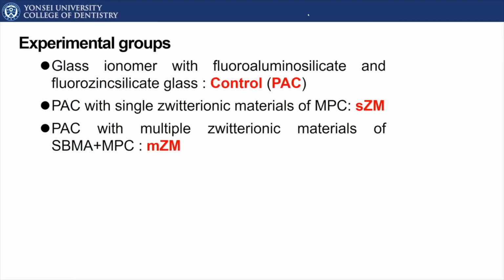So here, what we prepared was glass ionomer with fluoroaluminum silicate, but also fluoro-zinc silicate. So a zinc-containing glass ionomer, which was very recently developed. We wanted to have some very newly available glass ionomer materials. So we had this as a control, and we call this polyalkenoate cement, whatever it's called in medicine. And we had two different experimental groups with this control. We added a single zwitterionic material, which is MPC, we call SZM, and also multiple. So we had two different zwitterionic materials, which are SBMA and MPC. We call this control just the glass ionomer with fluoro-zinc silicate, SZM for MPC with this control, and MZM for SBMA plus MPC in this control.